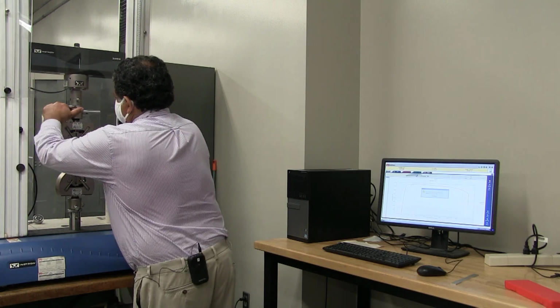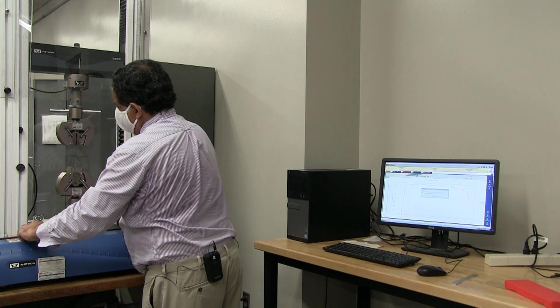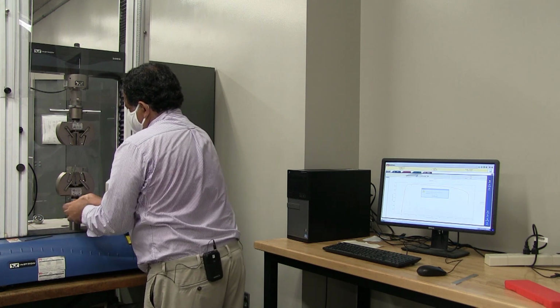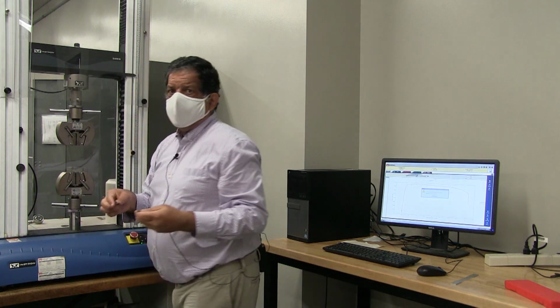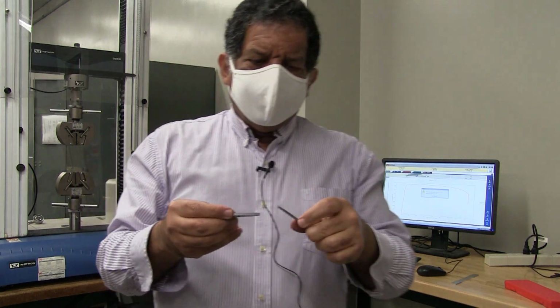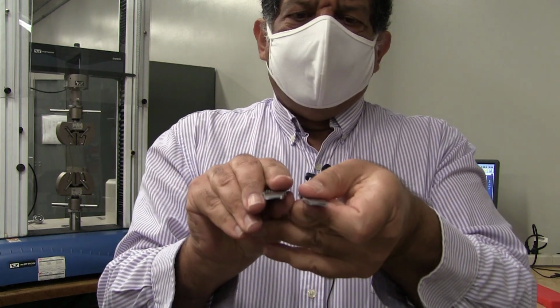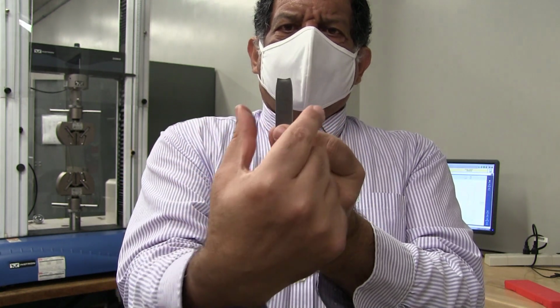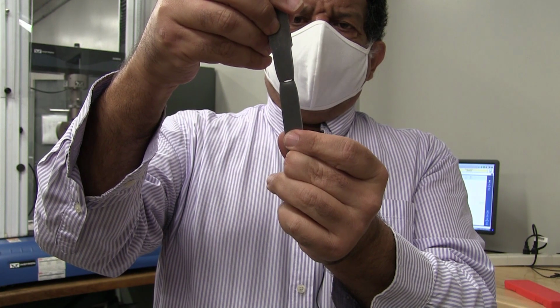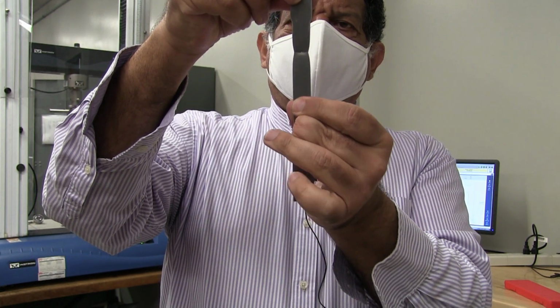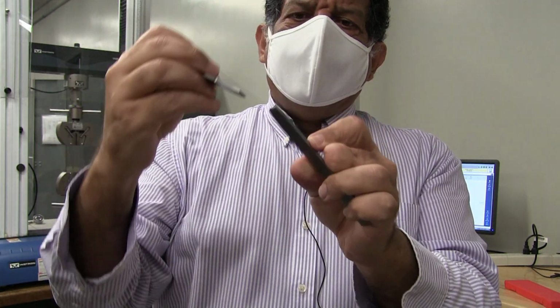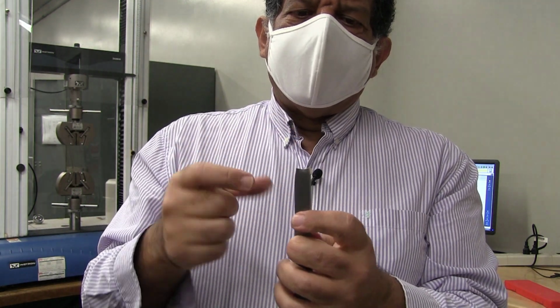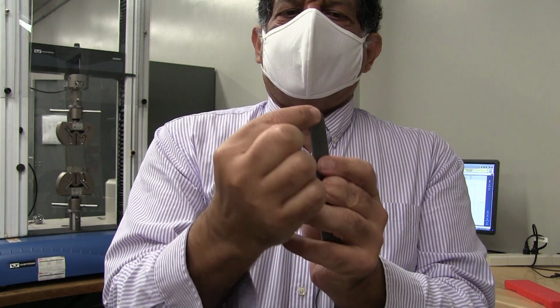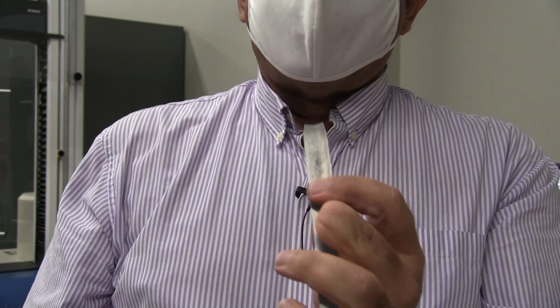unload the specimen, take it out. And you can see the fracture over here. You can see that there's been necking, and the area where the fracture occurred is significantly thinner than the rest of the specimen. And we're going to measure the percent elongation. We're also going to measure the thickness and the width of the fractured section of it.